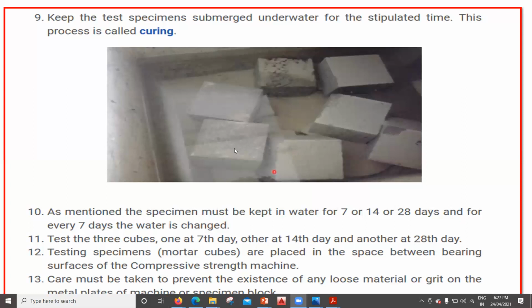You can see a kind of specimen here. This kind of specimen we shouldn't create. This is a result of not giving proper tamping and not doing the proper vibration. If you do proper vibration and properly tamp it, this is the kind of cement mortar that is required. Here, what has happened is a loss of paste. So even before testing, this is going to fail, right? That is why we should make sure the vibration is done properly and proper tamping is done.